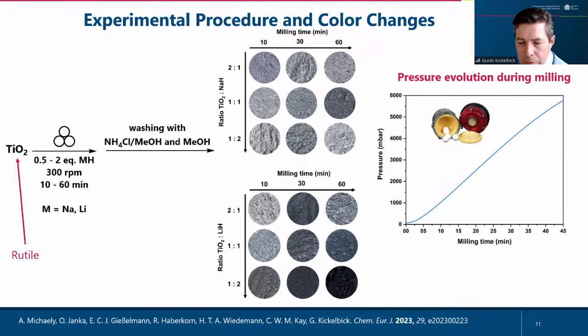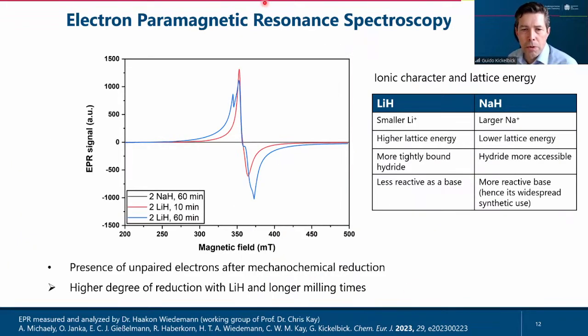The question was, did we really do the reduction? And as you have seen in the previous slides, EPR spectroscopy can help us here. With EPR spectroscopy, you can detect unpaired electrons, and in the case of titanium-3, you definitely have unpaired electrons. What you can see in this spectra is that lithium hydride, after 10 minutes and 60 minutes, was forming quite high concentrations of titanium-3. But sodium hydride, even after 60 minutes, didn't deliver any signal. So there, the reduction potential was much lower.